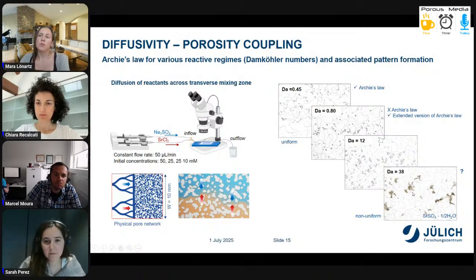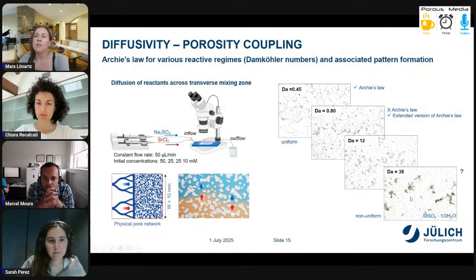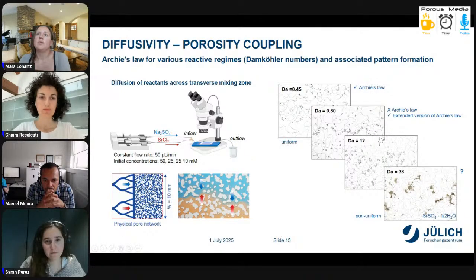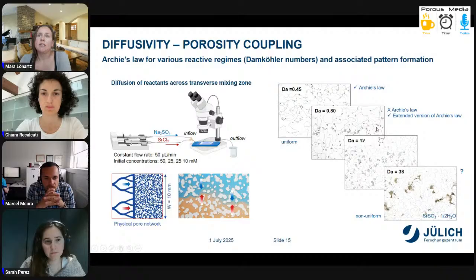more and more non-uniform, and what was really special is that at such high concentration, the kinetically preferred celestine, the intermediate phase of celestine, was precipitating, incorporating water. So what we can see here is that just a slight increase in the reactivity of the system made Archie's law not applicable for the system to predict the effective diffusivity.